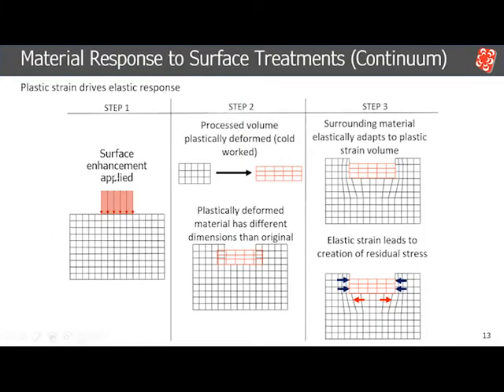So let's take that concept. We applied laser peening, we deformed the part on the surface of the material up to a specific depth, and now we're putting that deformed area into the material. So we're pushing a plastically deformed material into the existing matrix. The natural reaction for the material surrounding it is to respond elastically, as in try to push back that deformation. And that's what gives rise to the elastic compressive residual stresses from the laser peening process.